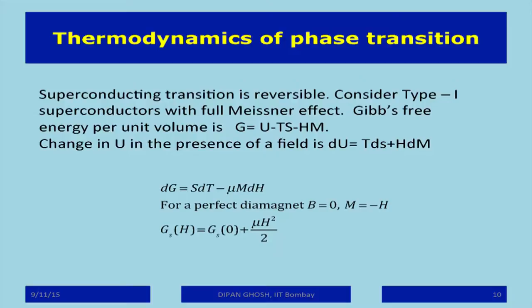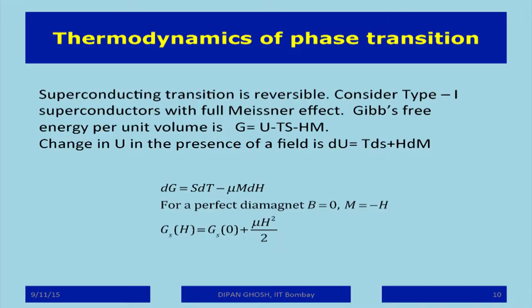There are 2 or 3 theories, a couple of them fairly elementary, and after that, of course, BCS theory, which is the most important theory. First is, the superconducting transition is obviously reversible. I can decrease the temperature, it becomes a superconductor, increase the temperature, it becomes a metal again. Okay? And I'm talking only about type 1 superconductors. Type 2 is a lot more difficult to understand. So in a type 1 superconductor, let me write down the Gibbs free energy. You all know the expression for the Gibbs free energy. So Gibbs free energy is U minus TS, there is a PV term, but of course, since the PV term remains the same on superconducting and normal side, I have not written it unnecessarily.